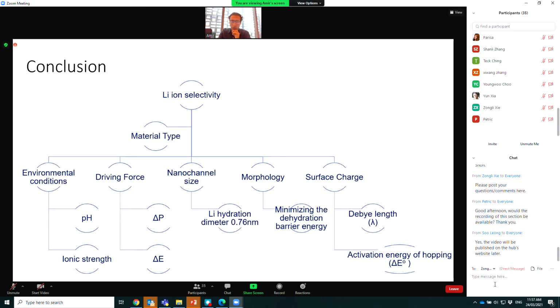So in conclusion, before I go to my last key take-home message: when it comes to using membranes as an element for DLE technology, direct lithium extraction, we have to create a good membrane that can transfer lithium at high rate, or gives us a good lithium ion selectivity, without compromising permeability. The most important thing is material type. We need a good material, and once you select it, you need to play around with a variety of parameters: environmental conditions, driving force, nanochannel and nanopore size, morphology, surface chemistry, and other things.